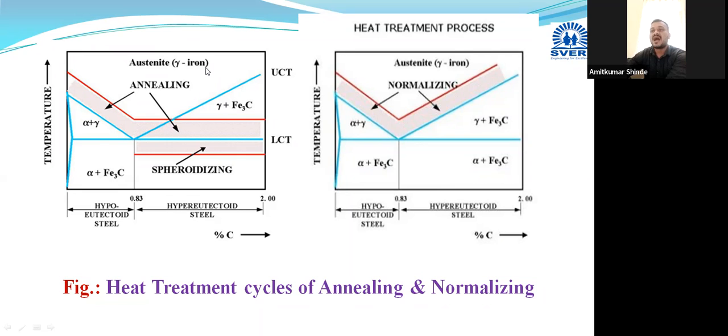Then, as in the hardening method we do rapid quenching, if you cool the sample from a very high temperature suddenly to room temperature or below, distortion, cracking, or warpage may occur in that component. And if you cool it suddenly in cold water from that high temperature zone, some warpage, cracking, or distortion may occur.